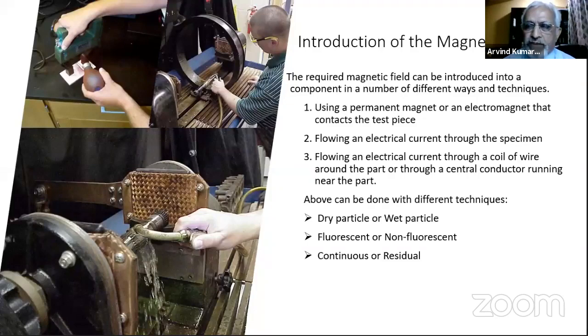Whereas a residual method would be, the part is very hard material which can retain magnetism, and you are magnetizing that part. Now, because of retained magnetism, you may remove the magnetic field. After that also, there is a lot of magnetism in the material, and you apply dry or wet particles; wherever there is an indication, they will attract and the indication will be formed. As I said, if you're doing a residual method, you have to make sure that the system is working.